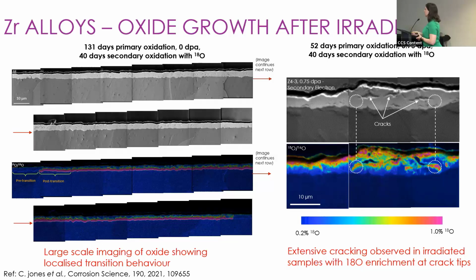So on the left-hand side here, we have a sample where the oxide was grown for 131 days in normal water, followed by 40 days in our oxygen-18-rich environments. This had no irradiation, and what I want to demonstrate here is how we've managed to start to map over larger areas of the sample. So all of this is actually one continuous piece of oxide. This image here attaches to the side just over here. So in some cases, we've managed to image over millimeters of length of sample of oxide. And so we're really now getting a much more representative view over the oxide.